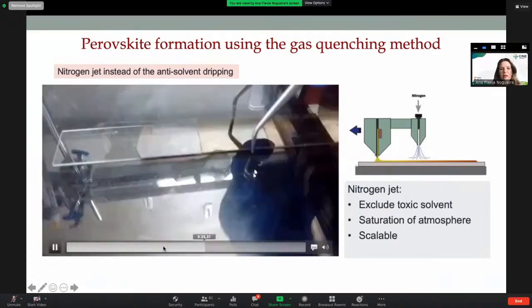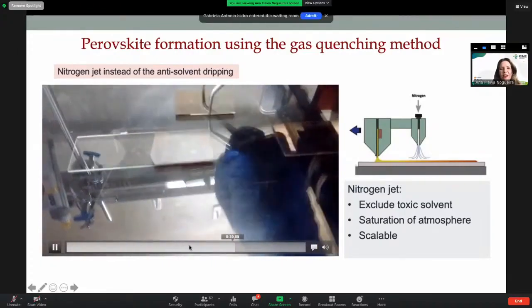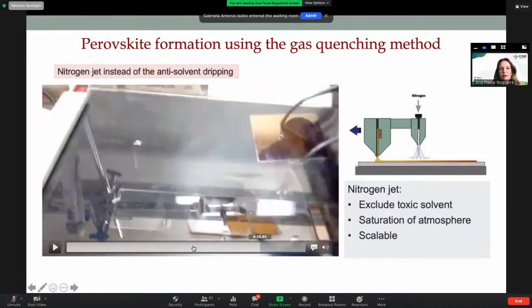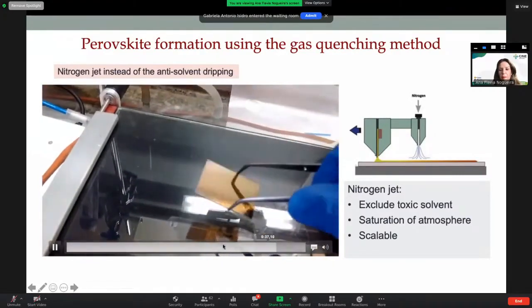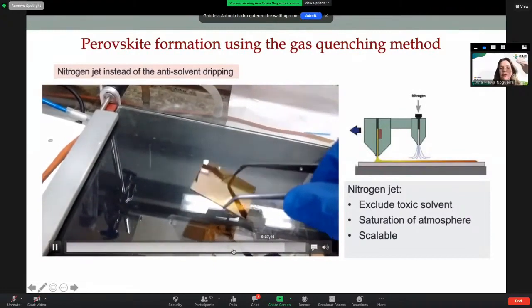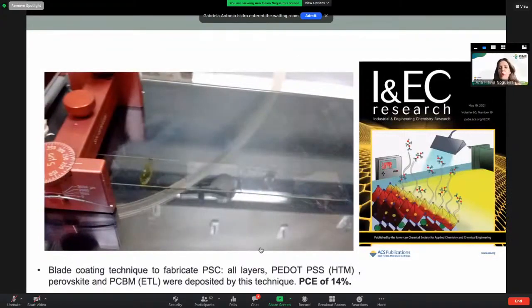You can see here that you can get a very, very nice film of the perovskite, very transparent. We use this film to prepare inverted perovskite solar cells, where all the layers were deposited by this technique. Not only the hole transport material, but also the electron transport material. And you got a PCE of 14%, which was covered, I think, in May of this journal, because all this method was done below 50 degrees Celsius, a very low temperature.